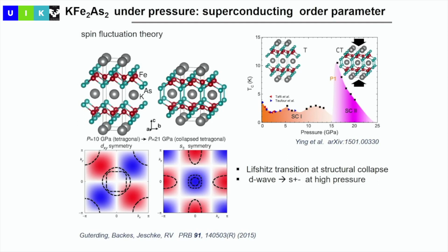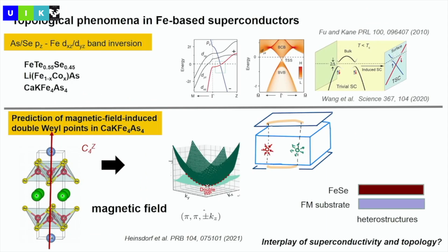calculation, the susceptibilities, the instabilities, and then the pair function, and then the gap function, the symmetry that you have for this case is a dxy symmetry. So the order parameter changes sign in a dxy manner, so plus, minus, plus, minus. So what happens is that at the phase transition, indeed, there is what we call a Lifshitz transition because the order parameter changes symmetry. So you go from a dxy order parameter to an S plus minus. And this is the kind of result that you can obtain out of these calculations where we assumed that the superconductivity is originated by these spin fluctuations. Now, this is my last slide. I wanted to show you, but I think I have no time anymore.